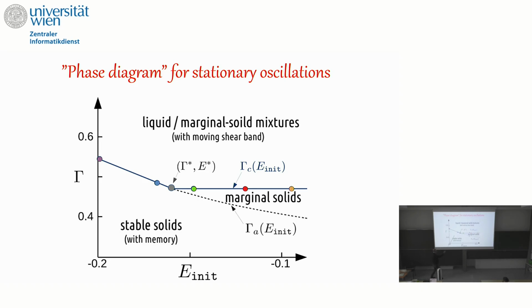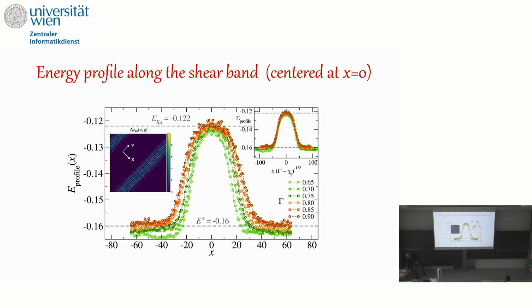So you have a solid-liquid transition. And the important point is that when you increase the value of gamma, especially if you are in the poorly annealed case, you forget your initial preparation and you arrive at a phase which is completely independent of the initial preparation, and all samples fail exactly at the same gamma star, except this very stable one, which fails at a bigger gamma star. Above it, you arrive at a phase that, at variance with uniform shearing, is completely dependent on the initial condition. And the last part is about this phase, so I think it is your point.